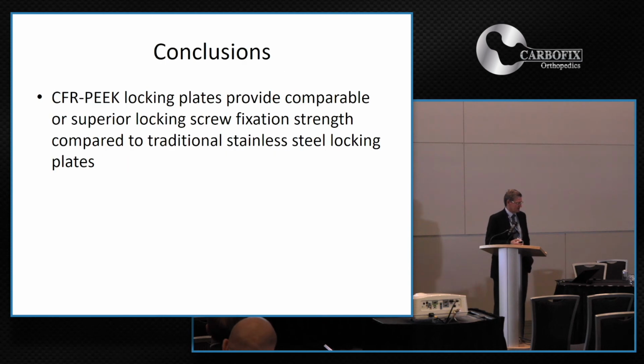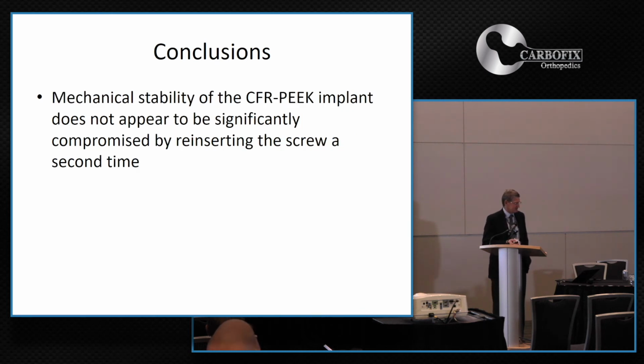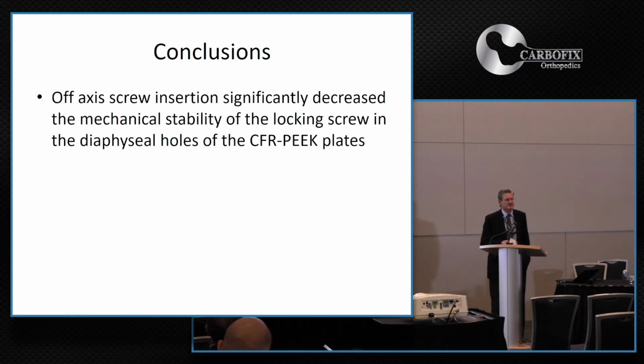So we concluded that the locking plate CFR PEEK were comparable or superior in terms of the engagement of the locking screw compared to traditional stainless steel plates, and didn't seem to be particularly detrimentally impacted by reinserting a screw into the same hole a second time. And again, off-axis screws, just like in other systems, are not going to be as mechanically stable as on-axis screws.